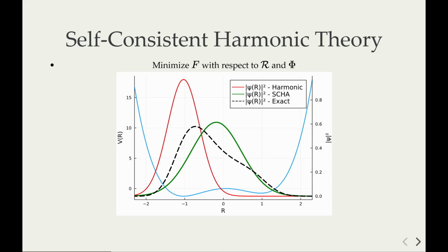Which is this Gaussian wave function here. Now we can take this wave function and use it to minimize the free energy of the system. If we perform this, we end up with this green line, while the exact solution, if we solve this potential numerically, gives us this black line here. So this is more or less how the method works in a simple one-dimensional case.